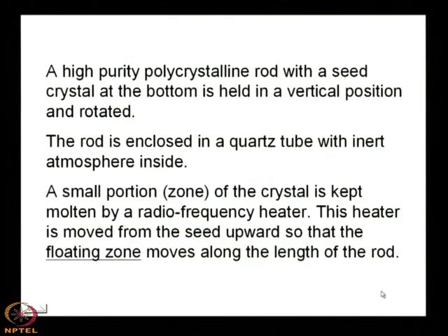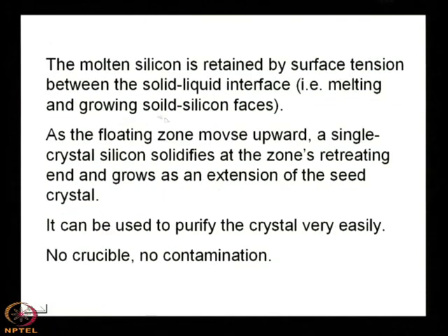And it moves along the length of the rod, and you see that this molten silicon is retained by surface tension between the solid-liquid interface, that is the melting and growing solid silicon phases. There are two phases: one is the growing, that means where it solidifies, and another is the molten, that means where the RF coil is. Because of the surface tension between these two interfaces, it is held there, it does not detach from its position.